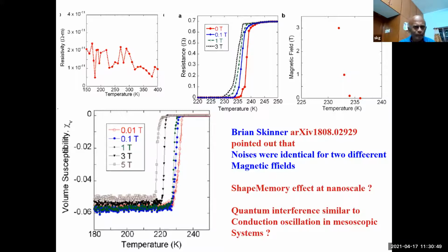And more importantly, as I said, there is a volume susceptibility, which is diamagnetic. So it falls down sharply, and it's very magnetic field dependent. So you can change it up and down. And they found noise which was much above experimental resolution. And Brian Skinner, a friend, immediately observed that there were 2 magnetic fields for which the noises were identical. So he was worried about the validity of the data. So he wrote a paper on the arXiv.